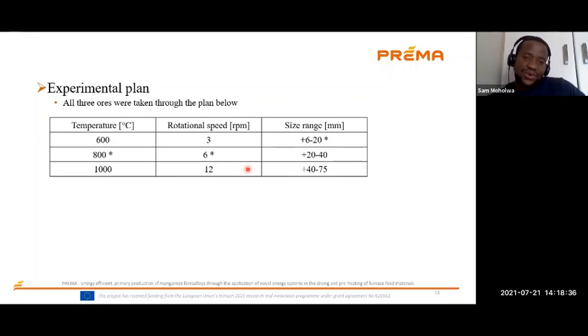This here was our experimental plan. All those 3 ores, A, B, and C, we mentioned before, were taken through this experimental plan. We investigated the effect of temperature, the effect of rotational speed, and the effect of size range, as we mentioned in our research questions earlier. When we were investigating the effect of temperature here, the rotational speed and the size range were kept constant at 6 RPM and the size range at +6, -20 millimeters.